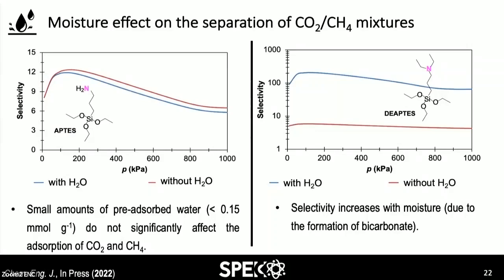And you can see that changing the nature of the amine changes dramatically, because, for instance, for the primary amine, there is no significant effect on the selectivity towards CO2. Under wet or dry conditions, it's more or less the same. But if you go to the tertiary amine, there is a huge difference. And so the selectivity increases with moisture, possibly due to the formation of bicarbonate.